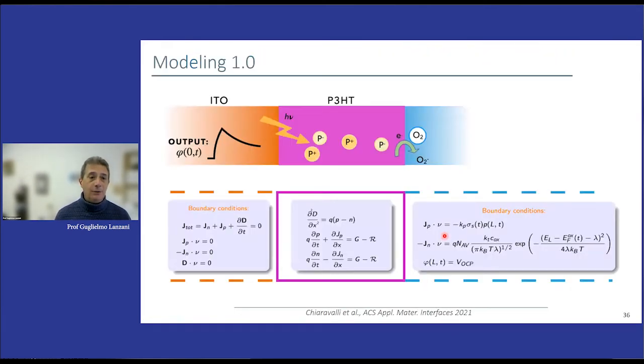Now, the model is the following. In the polymer, we consider the charge generation and the recombination and the current of the charge carriers, which are in these two equations here. And then we consider the Poisson equation for the field. So we take into account that there is an electrical field, and this field is affected by the charge generation process and by the charge motion. So it's a drift diffusion equation that we are using with a boundary condition that takes into account on the left the situation at the ITO, and we assume that charges are not entering the ITO. And on the right, we assume that there is an electron transfer to oxygen, which is in the electrolyte.